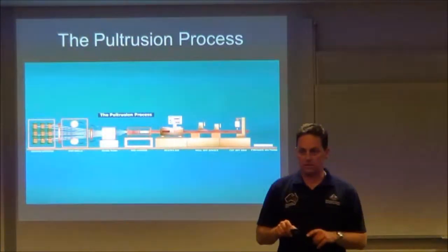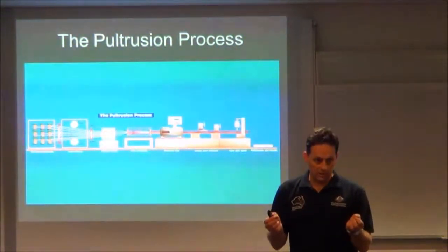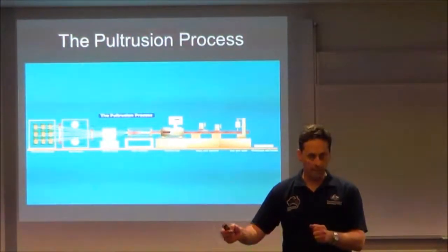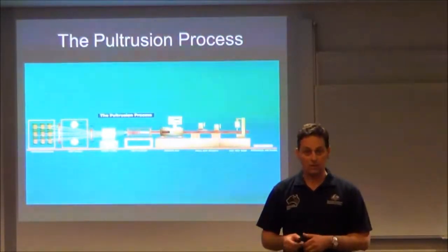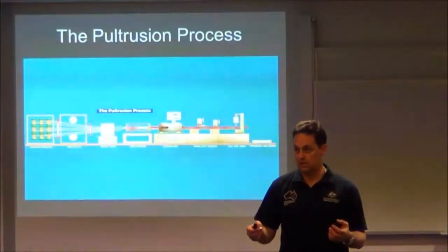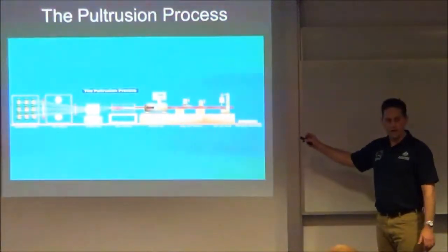The other thing that's really important to understand is it's a thermoset polymer that goes around the bar, so the resin's thermoset. So once it's manufactured, that's it. You don't put a blowtorch to it on the building site and bend it. It has to be bent in factory. That means it needs to be scheduled well and understood well by an engineer beforehand. So it might have to be shop drawn, so you've actually got those pieces of reinforcing, the bends, the cogs, the ligatures. They're all understood, they're named, they've got accurate details of what they are. You know numbers of them so they can be ordered and they arrive on the building site. So no tack welding? No. No. You can try.